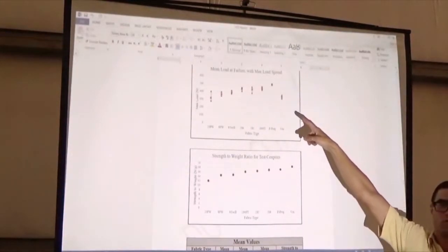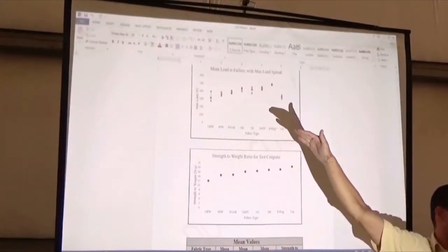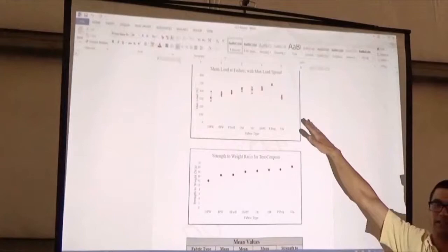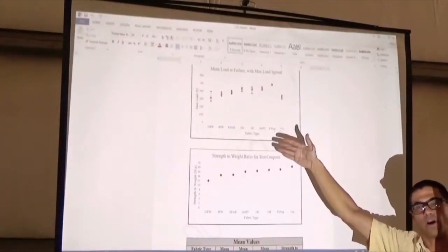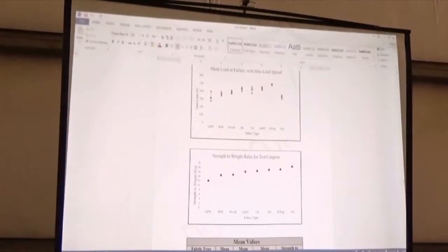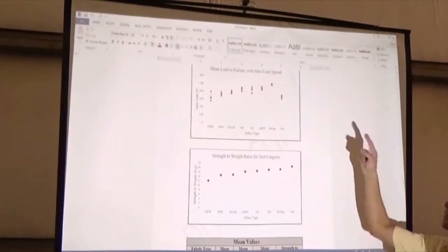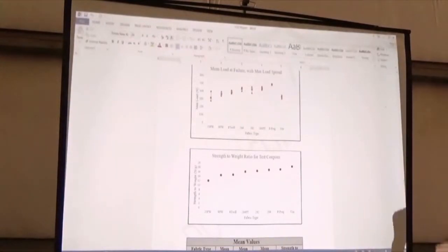So this is a really tight spread, and what that means is that if you're designing a structure and you have a margin of safety, theoretically you could use a lower margin of safety for a pre-preg than you would for a wet lay. Or conversely, you would need to use a higher margin of safety for a hand-laid wet lay compared to a pre-preg. And so if you can use a lower safety margin on the pre-preg, you can have a lighter part.